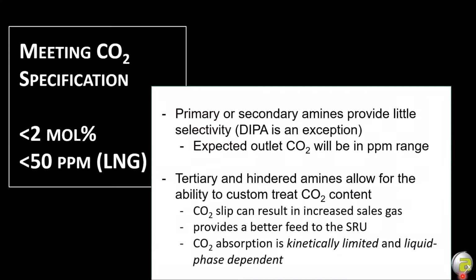Primary and secondary amines, like MEA or DEA, react very strongly with CO2, so we tend to leave ppm ranges of CO2, so they can easily meet a pipeline spec. Tertiary amines, which is MDEA and the like, and hindered amines, things like Flexsorb, allow for slipping some of that CO2, so we can custom make our process. Now, especially with MDEA type solvents, which most of us are using nowadays, the CO2 absorption is kinetically limited. The warmer the temperature, the more CO2 reaction there is, but obviously the warmer the temperature, the less capacity the amine has. So we have to always be concerned about temperature. And we tend to say it's liquid phase dependent.